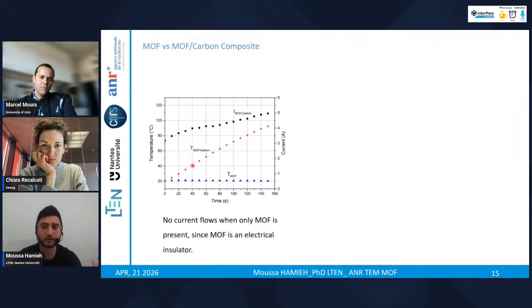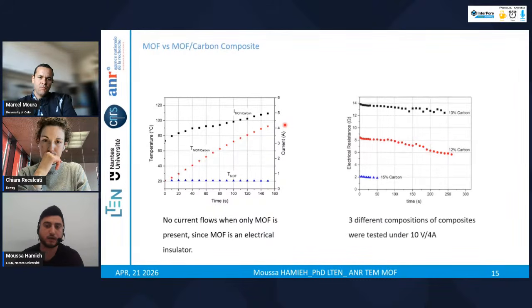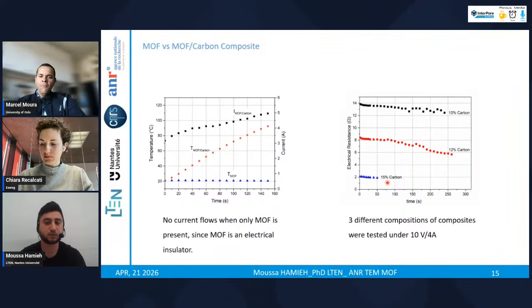However, when we added the carbon, we can see clearly that the current flows inside the MOF carbon matrix. And we see that the temperature is significantly increasing to the desired temperature for the desorption step. So this confirms that the carbon enables the electrothermal in-situ heating for the composite. To understand better, we also analyze the electrical resistance of the different composites for 10, 12, and 15% of carbon inside the composite. We see that with higher carbon amount, it is more electrically conductive, and we have lower electrical resistance. And at the end, it will depend on the voltage and the current applied to reach the desired temperature.